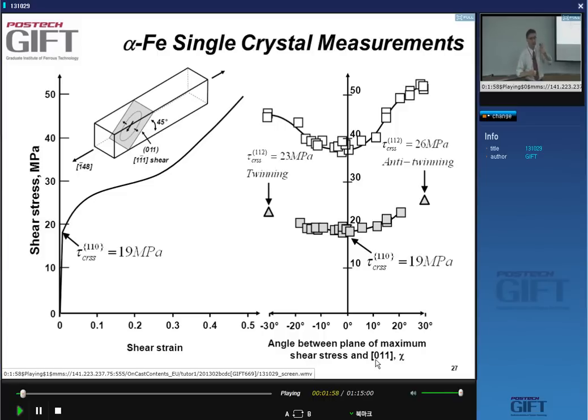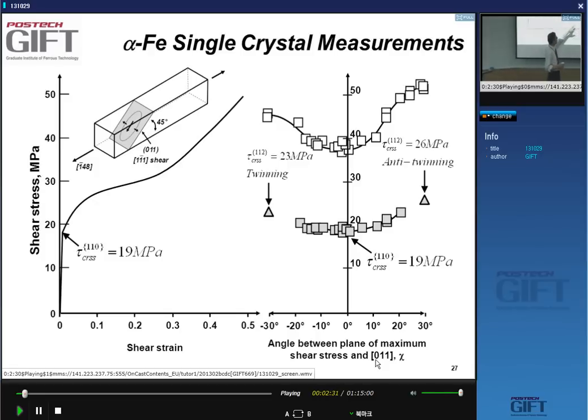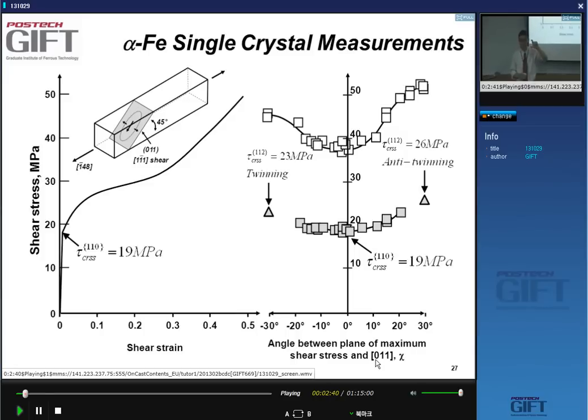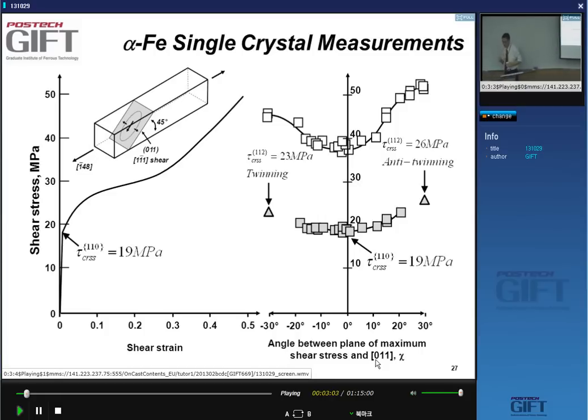But with steel it's complex. So first let's look at what we measure experimentally. If you take a single crystal, you orient it in a way that makes sure there's only one slip system that works — for instance, one Burgers vector and one 110 plane. You find, when you actually measure it in compression, a yield strength of 38 megapascal. Then you recalculate this using the Schmid factor, and you find 19 megapascal is the critical shear stress — a fairly low value.